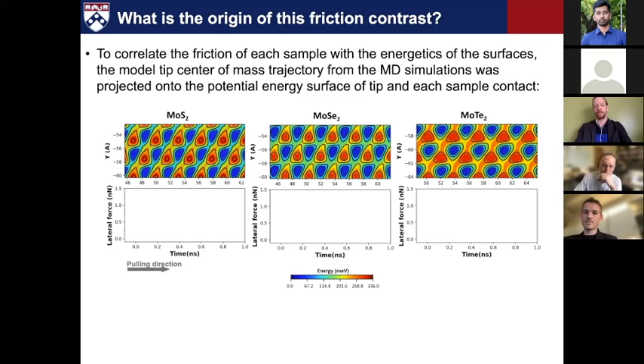As you know, MoS2 and this sort of transition metal dichalcogenides are very sensitive to strain. So is there any possibility that while you are loading with different pressures, strain got induced and accordingly their local conduction changes, because in that case, local conducting atomic force microscopy could give you a good contrast effect.